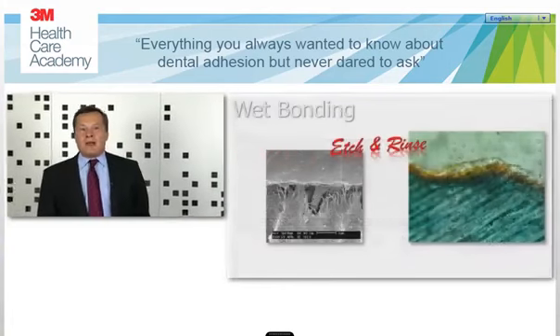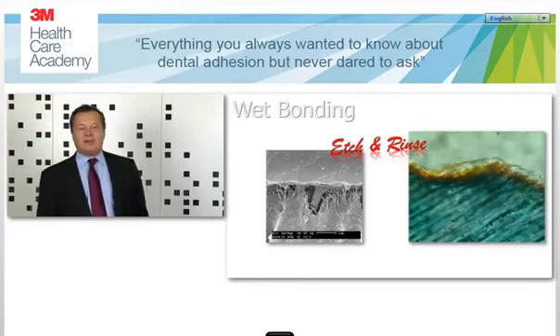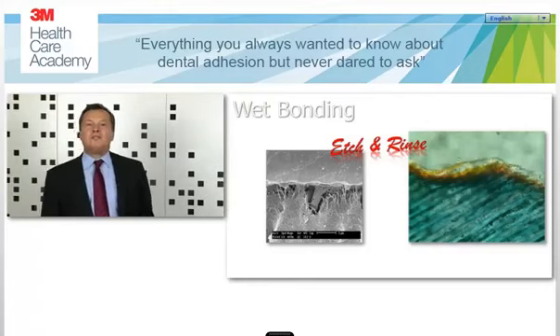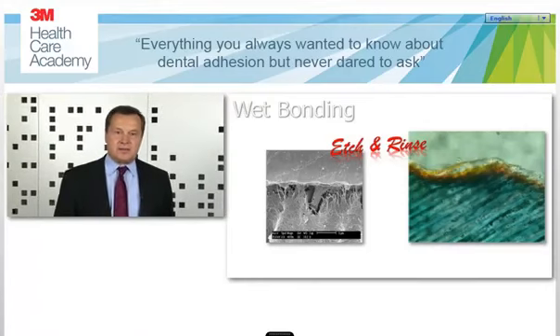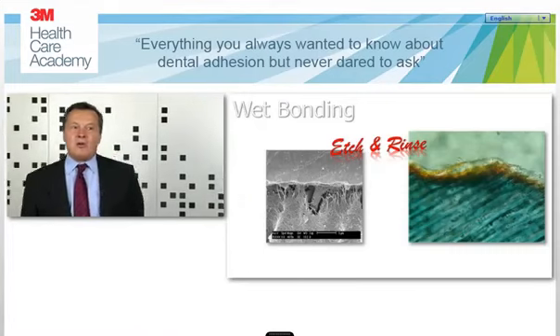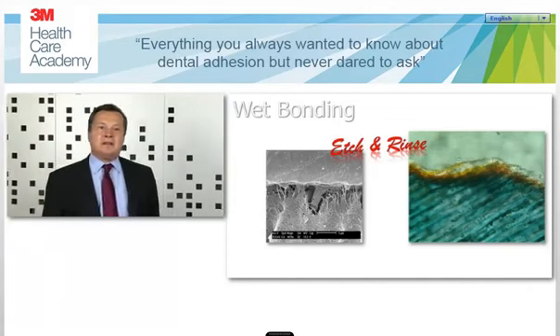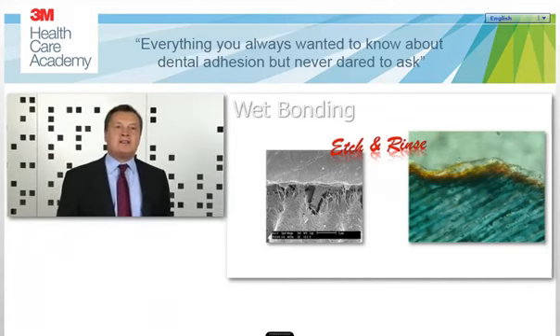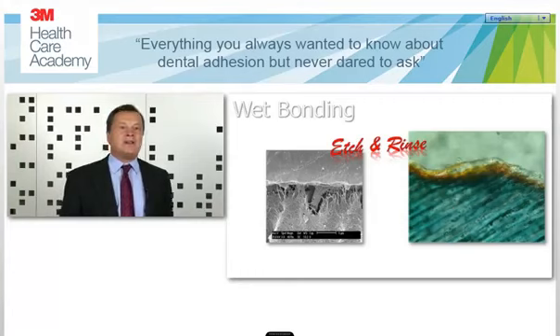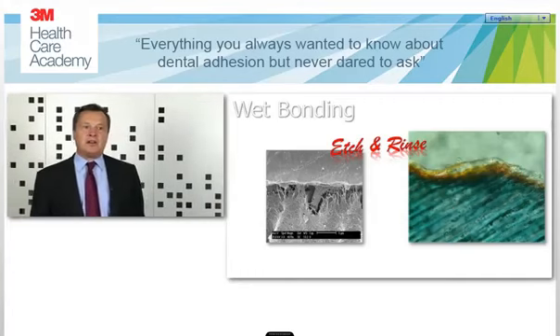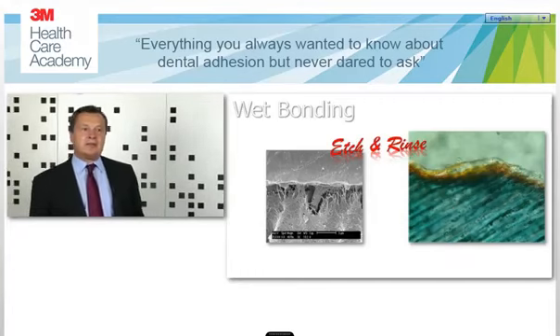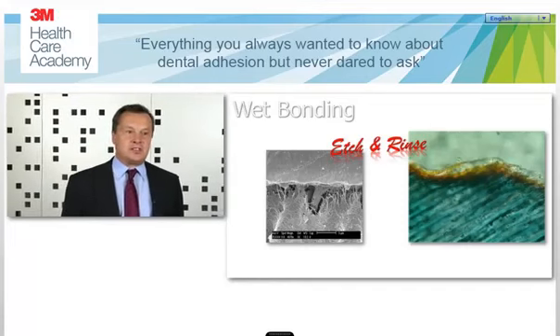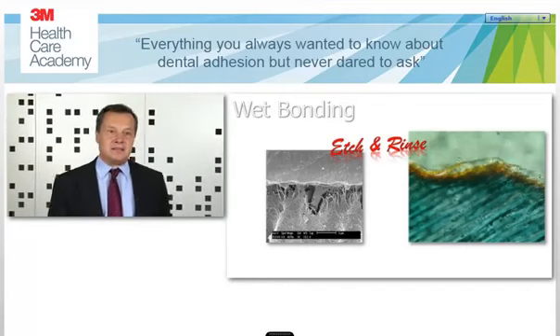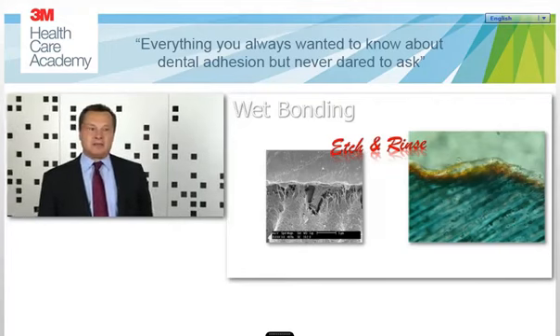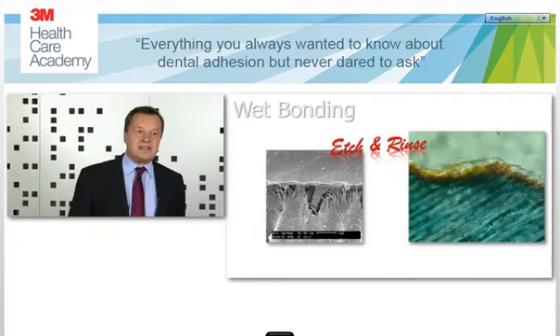Now, when applying strong acids on dentin, there is always the danger of over-etching this dental surface, because there's a very, very narrow window of opportunity in respect to the time where dentin is really optimally etched or when it can be over-etched. And very often, by applying phosphoric acid, it is a little bit over-etched, meaning that you demineralize dentin and you expose collagen fibers, as is shown on the left-hand side of this slide.